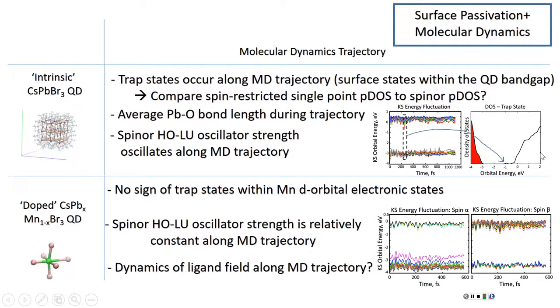So then spin restriction is really important even when you don't have d orbitals from manganese. Ideally, one should do everything with spin orbit, because you have lead and bromine. Yes, that's why. Especially if it was shown possible, then it is more correct scientifically, with less danger of being hit by all the criticism. But your dynamics is done with the spin restricted case, right? Right.